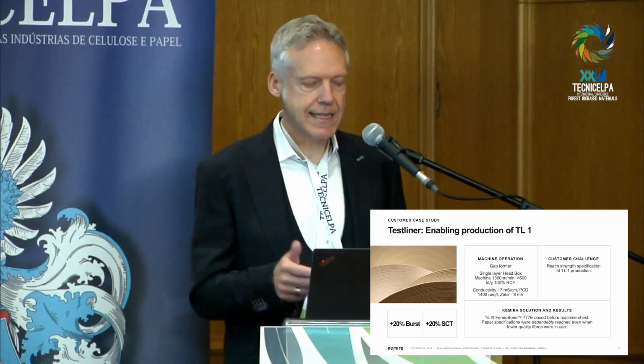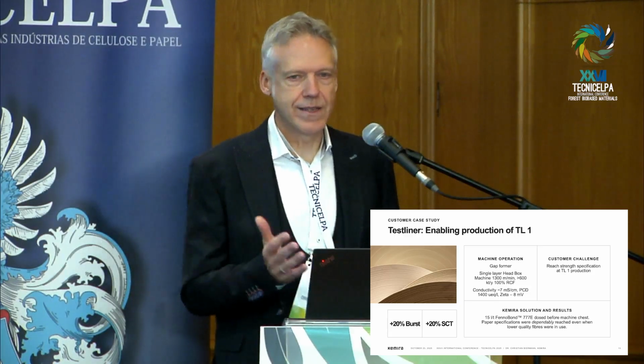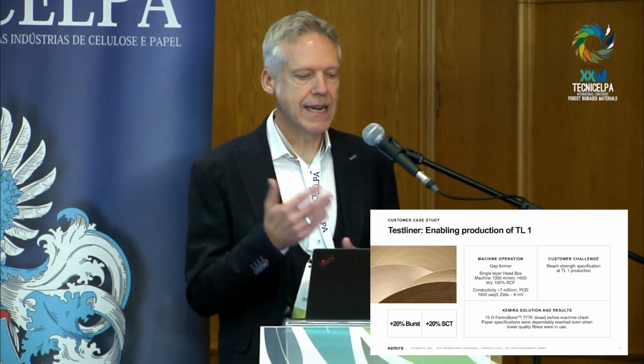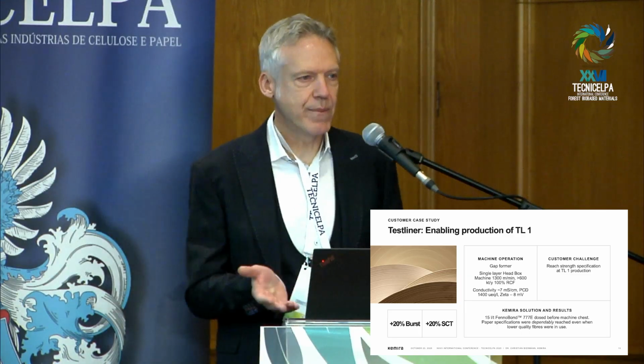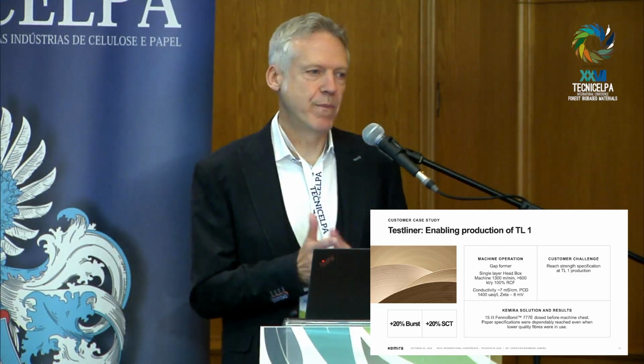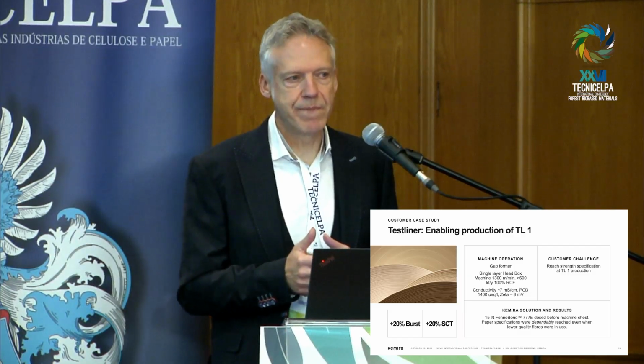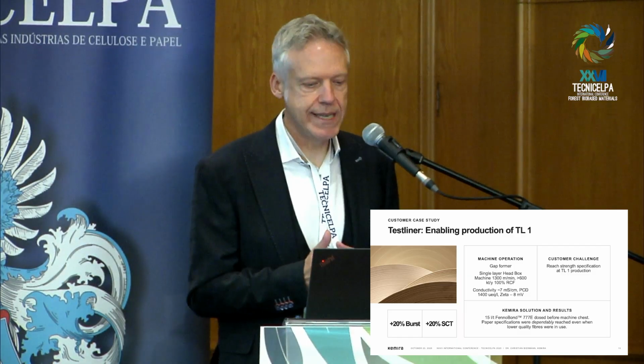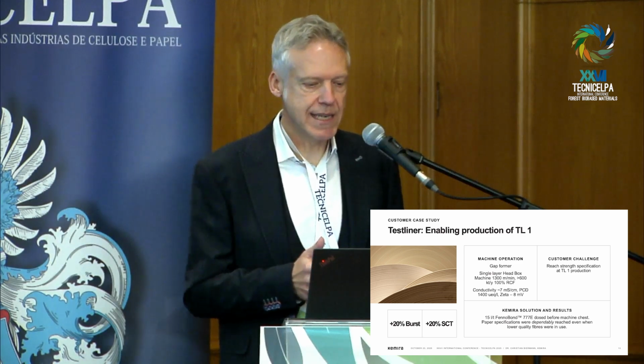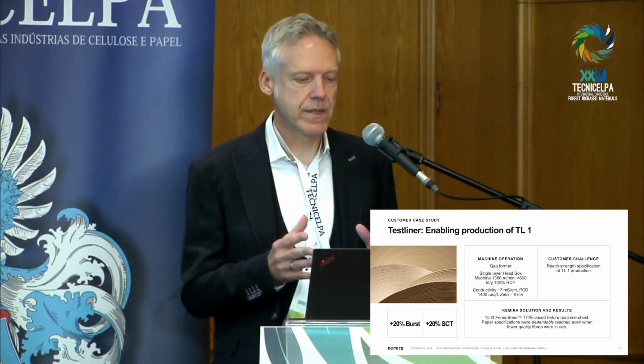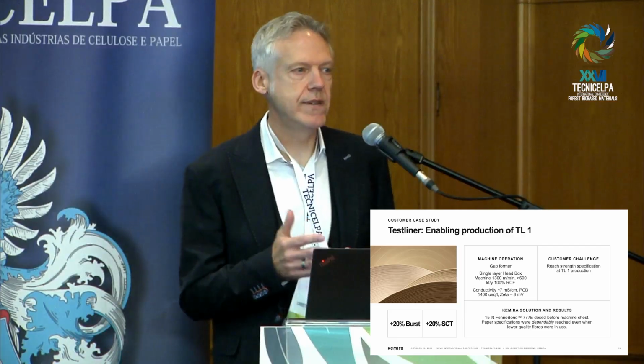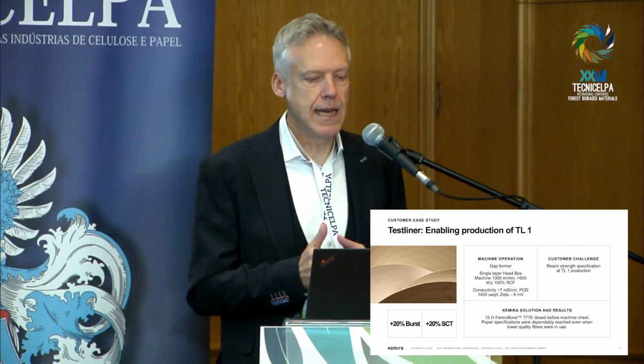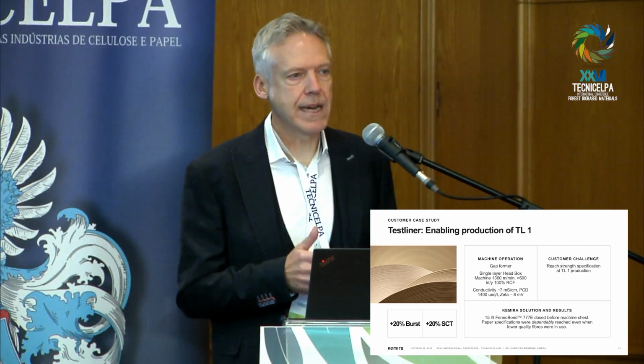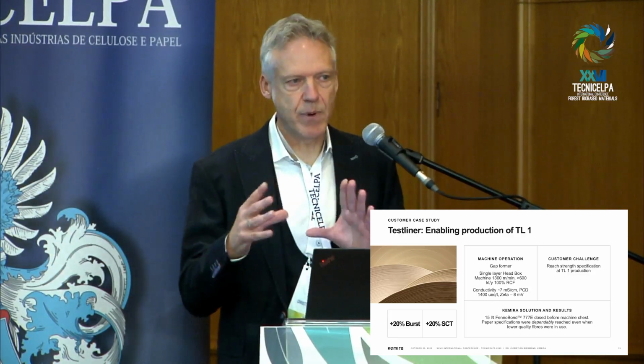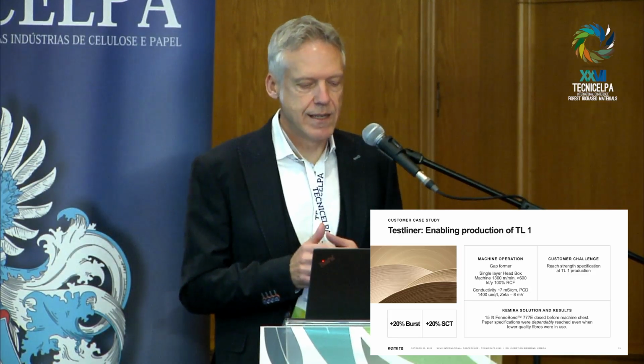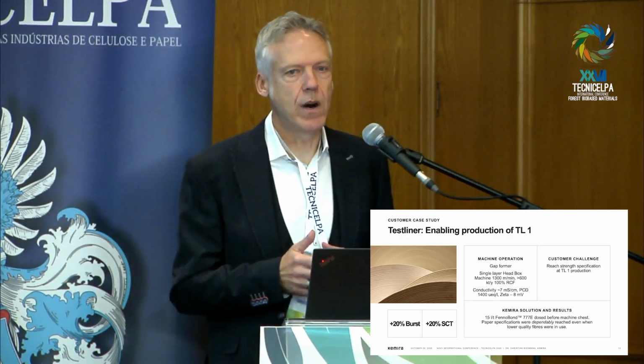Okay, last case study is testliner. Here we are the complete opposite of virgin fibers, so 100% recycled fibers. It's a modern machine, less than 10 years old, producing more than 600,000 tons per year, speed 1,300 meters, and the system charge is quite extreme. Conductivity 7 millisiemens per centimeter, and colloidal load 1,400 microequivalents per liter, and those are the headbox measurements. Zeta -8, but I think that is pretty normal for an RCF mill.